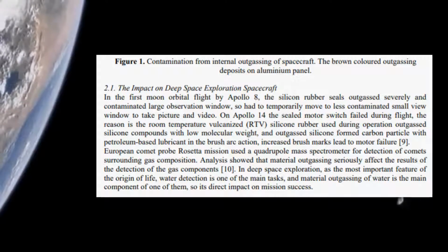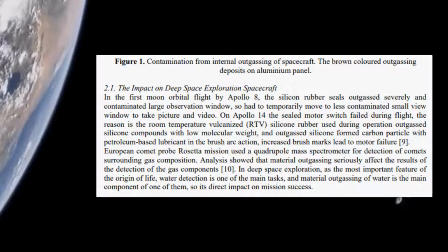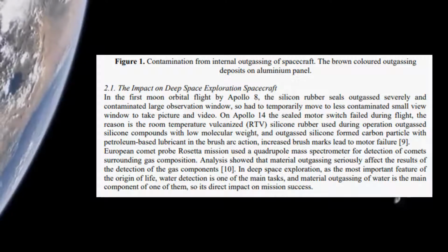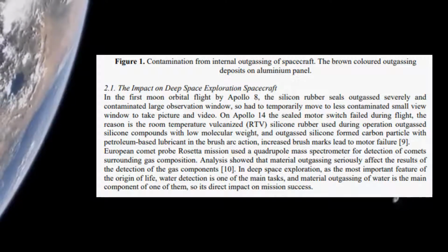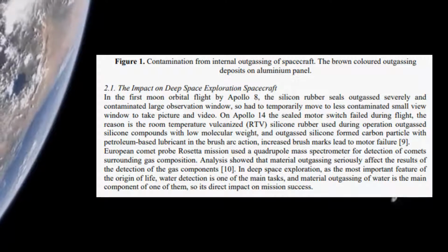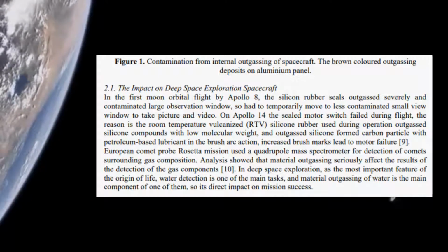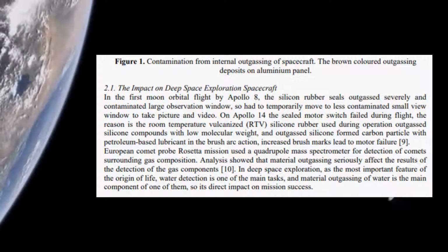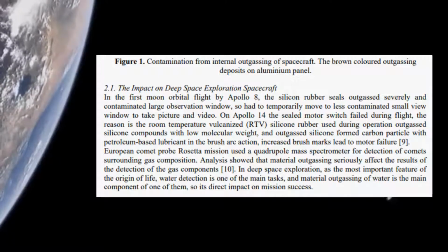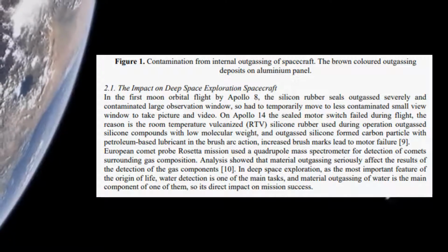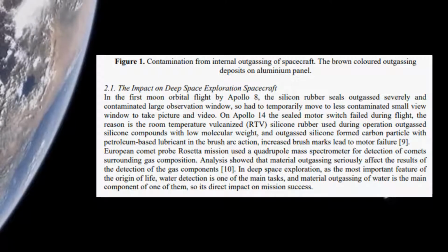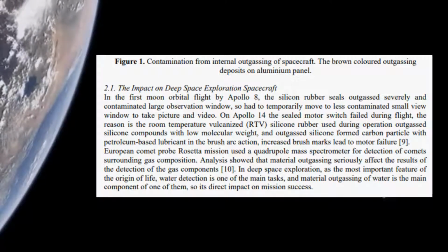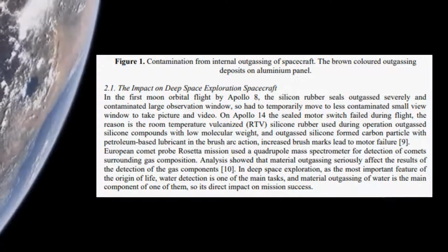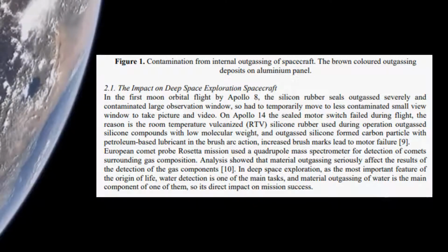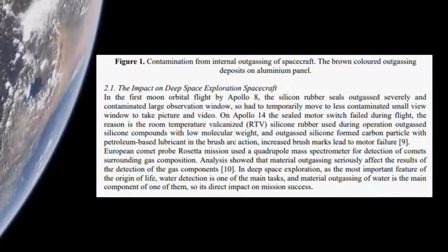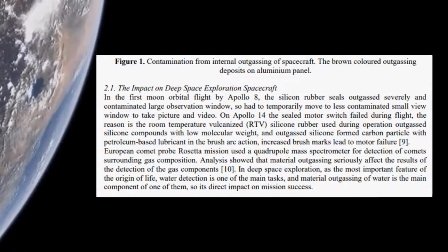Increased brush marks led to motor failure. The European comet probe Rosetta mission used a quadrupole mass spectrometer for detection of the gas composition surrounding comets. Analysis showed that material outgassing severely affected the detection results of the gas components. In deep space exploration, water detection, as the most important feature of the origin of life, is one of the main tasks, and water outgassed from materials is one of the main components, so it directly impacts mission success.